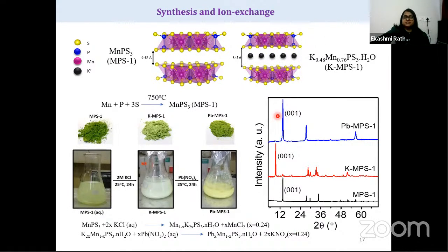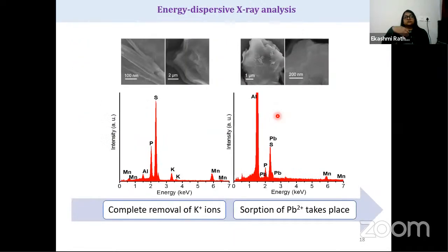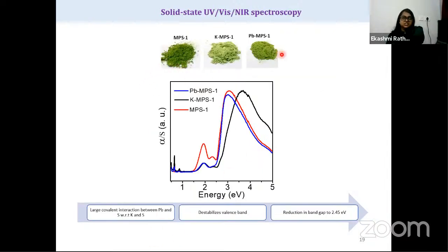This is a classic characterization technique which we use in laboratories to find out whether lead is going into the system or not. Then I conducted energy dispersive X-ray analysis, which tells us what kinds of elements are present in the compound. These are the scanning electron microscopy images, and here you can see that potassium is being replaced by lead ions, which tells us there is complete removal of potassium ions and sorption of lead takes place. Here we see the color change, and the band gaps tell us that there is larger covalent interaction between lead and sulfur than between potassium and sulfur, which destabilizes the valence band, and there is a reduction in the band gap to 2.45.